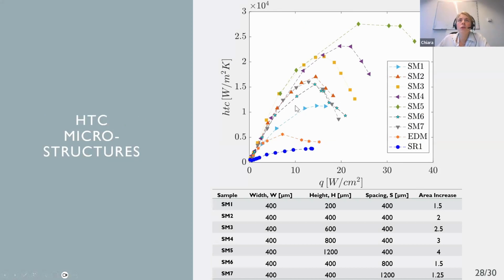This improvement is also clearly observed in the heat transfer coefficient, which increases with the height of the pins. But interestingly, if we look at SM2, SM6 and 7, which correspond to structures with different spacing, so same thickness and same height of the structures, but just different spacing between the arrays, we can see that in the end, this doesn't have a huge impact on the heat transfer coefficient, at least for the spacings tested, while the height has a much higher impact.